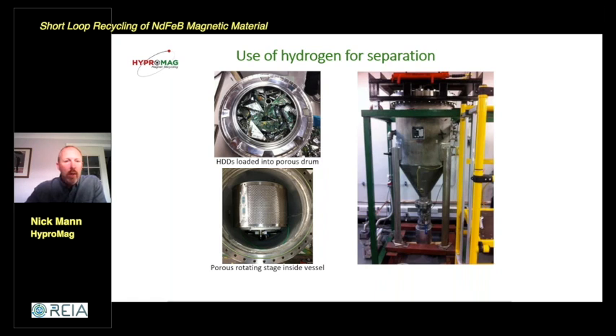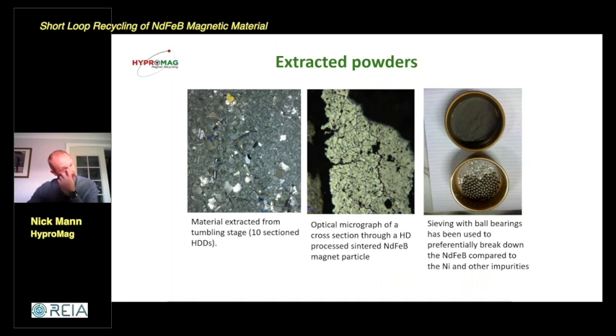So as the powder is generated from the reaction, it can fall through the holes in the porous drum, and it comes down into a collection pot at the bottom of the vessel. Those holes in that porous drum are about 3 millimeters in diameter. So that means that the material that we get out contains everything which has got a size smaller than 3 millimeters. So there's nickel flakes in this powder, there's occasional small screws, there's bits of plastic. But when you look at the lumps of NdFeB that have come through, that reaction has taken place even through those larger lumps of NdFeB. You can see the grains are starting to split in the middle picture.